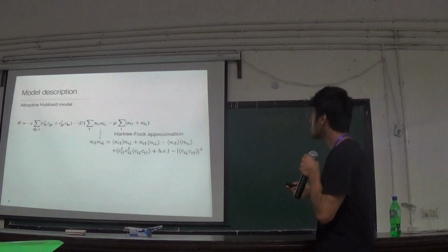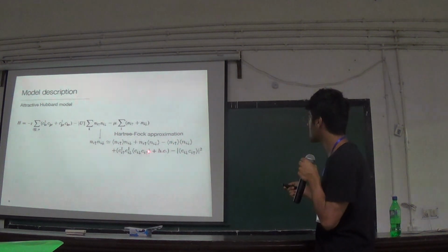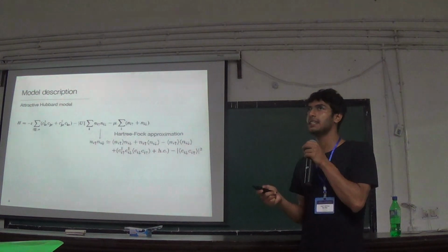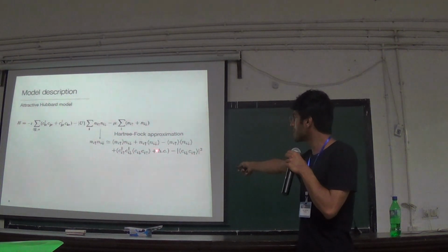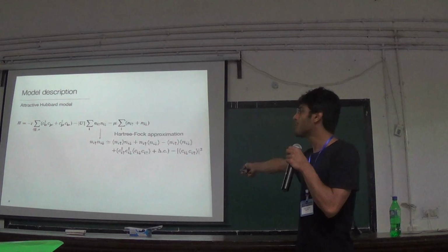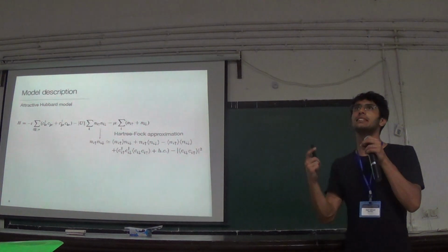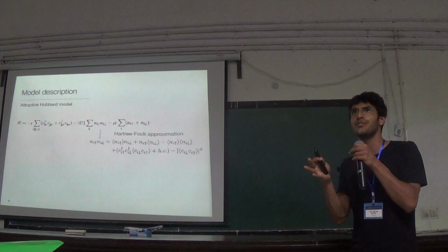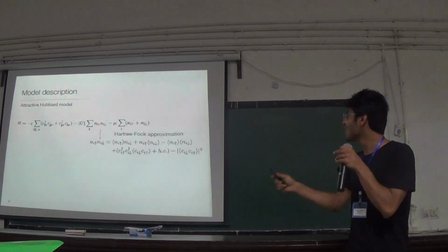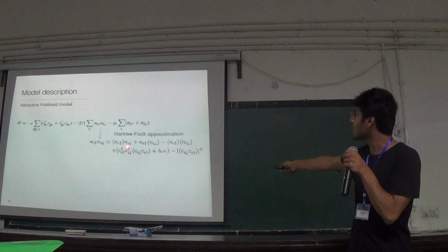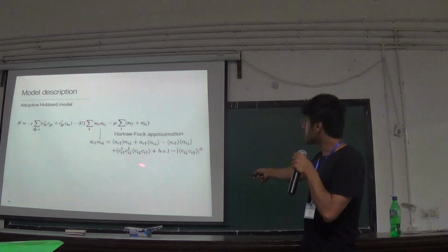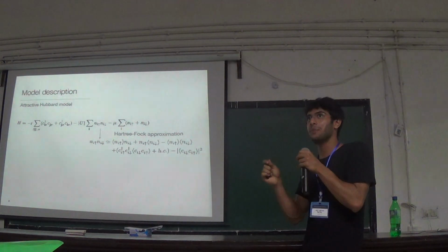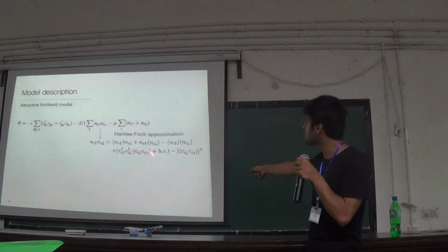So notice that in the usual case we drop these terms, and that's due to the fact that the ground state is the Fermi surface. What is happening here is that these are two annihilation operators which will kill two electrons over here, and then this part will come and that will give you zero for a Fermi surface. But since I said that there's an instability in the system, now you know that the ground state is not really the Fermi surface, it's something else. You don't know about that. So you can't really say that this is zero. That's what you keep, and since this is non-zero, you know that something's happening to the Fermi surface. So you can even relate this to the order parameter also.